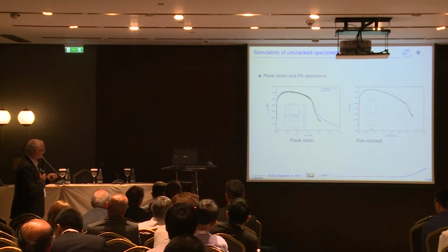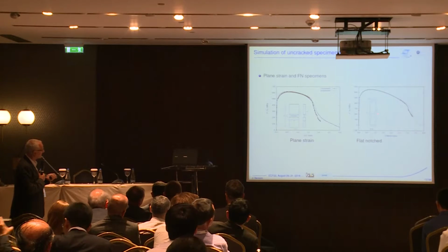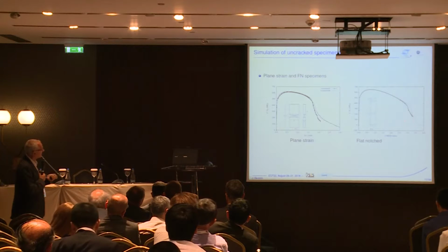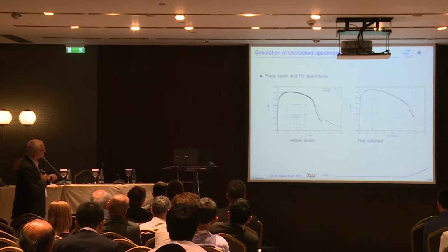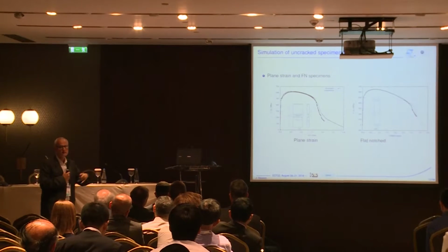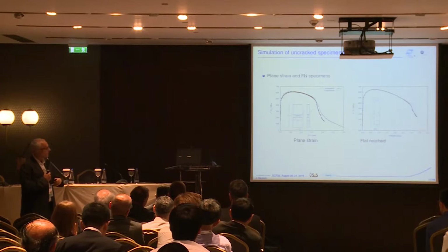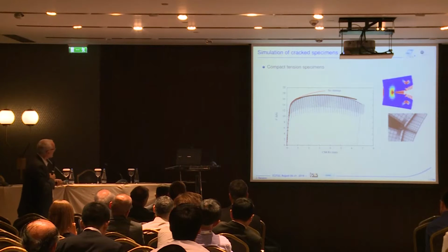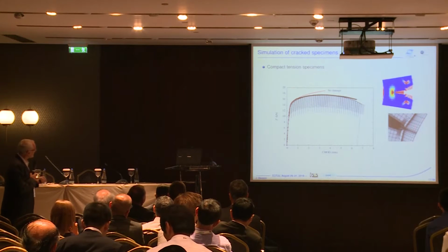This is a flat specimen with notches, and we also get good agreement. And this specimen is somewhere in between, in terms of stress triaxiality and load parameter, between the plane strain and the axisymmetric specimen. So let's move to the CT specimen.